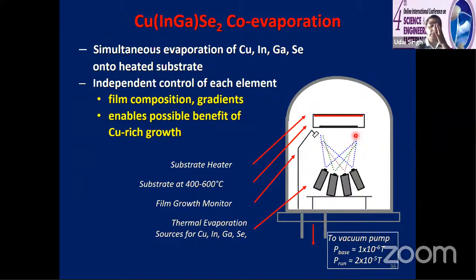So I will just discuss co-evaporation. That is a facility available in my lab also. Like you have the 4 sources, which are thermal evaporation sources for the copper, indium, gallium, and selenium. So you can always change the flux also, depending on how you want to tune the profile of this. And then you have the substrate, and the substrate is heated to around 500 to 550 degrees C.